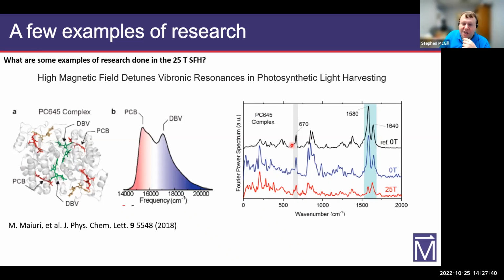There's some periodic oscillations in there. And the period of them is proportional to the energy separation of the overlapping excited states. And so we see those here, and these are the different energies in wave numbers of what those are. There's one here that's a reference that has a portion of it removed, but here are the two identical chromophores at 0 field and 25 Tesla. And you can see that the amplitude of this signal is a sign of how strong the resonance is between those two excited states.